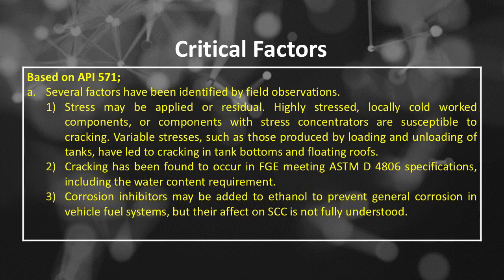Number 1, stress may be applied or residual. Highly stressed, locally cold worked components or components with stress concentrators are susceptible to cracking. Variable stresses, such as those produced by loading and unloading of tanks, have led to cracking in tank bottoms and floating roofs.